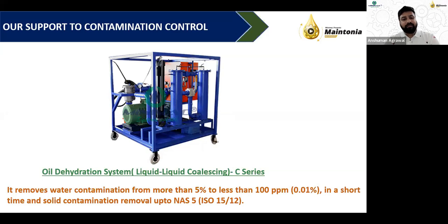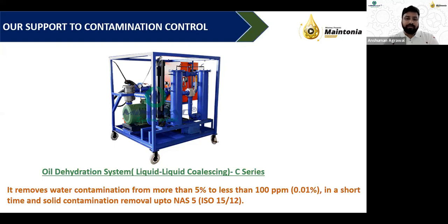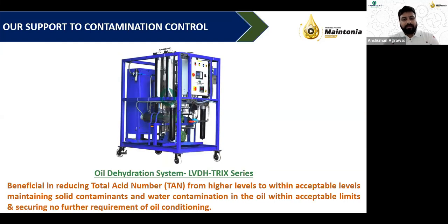A dehydration system using coalescer technology reduces free water contamination quickly, at high flow rates, and with minimal maintenance. Additionally, systems using ion exchange-based technology can reduce the Total Acid Number (TAN) in synthetic oils, addressing not just solid and moisture contamination but also acidity.